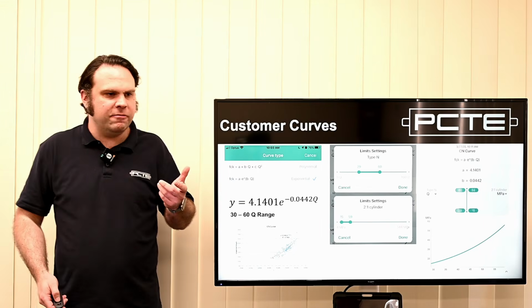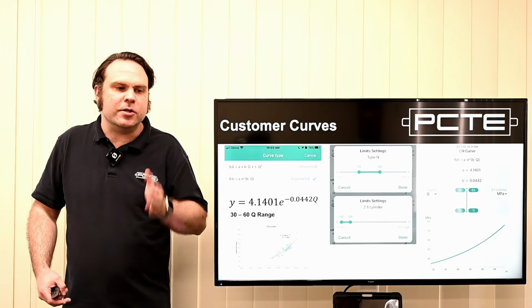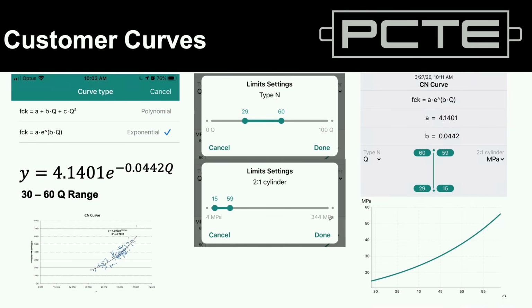So that custom curve functionality is then going to let you set the upper and lower bounds. And you want to set this as the lowest and highest cylinder break you've got, because we can't extrapolate the curve down or up. We don't know how it's shaped. We don't have the information below that point or above that point. And then that's loaded in the hammer, and it will produce an MPa conversion between those values, just like with the manufacturer curves, but it matches your material.